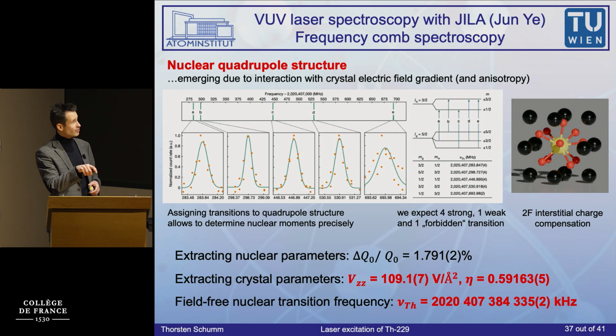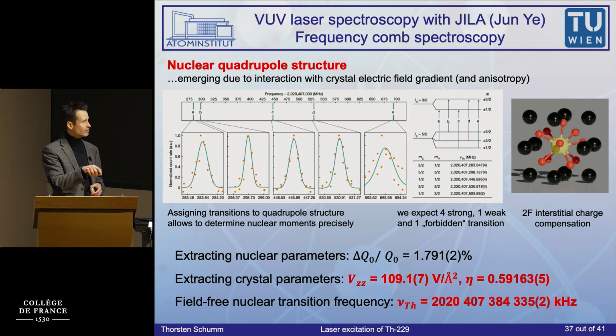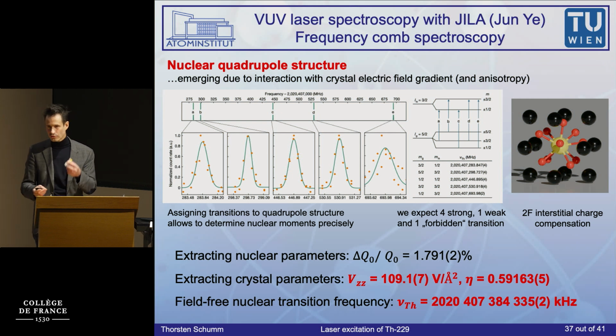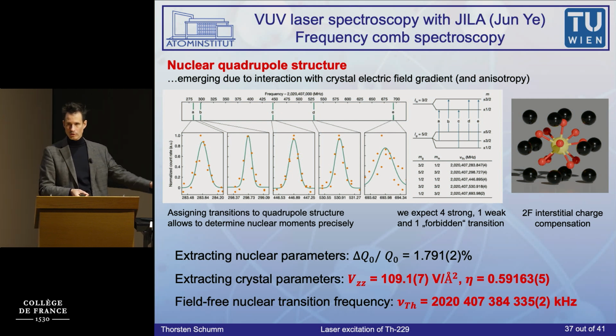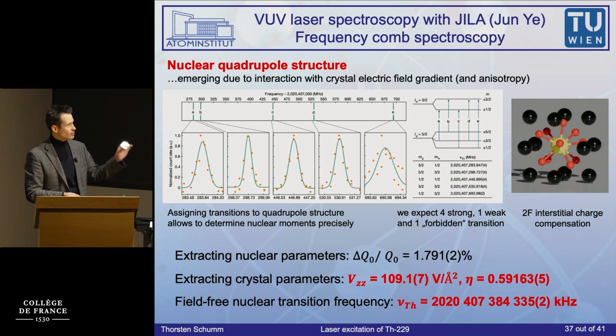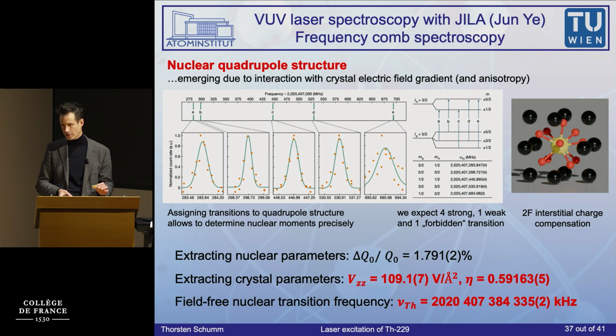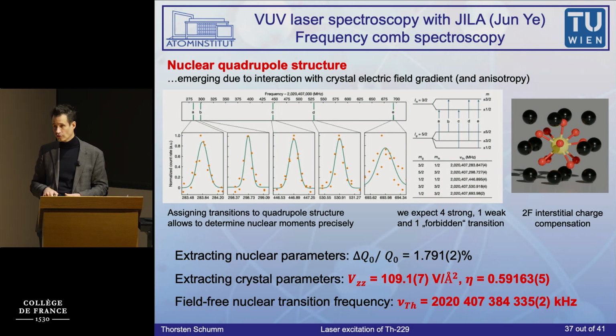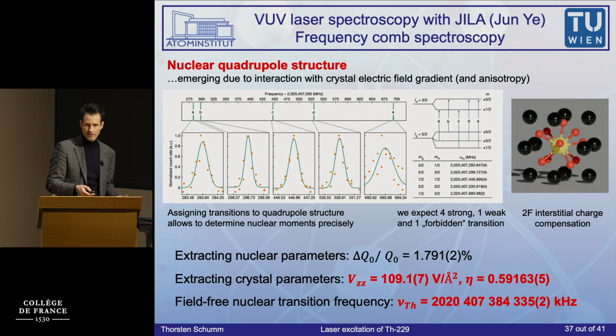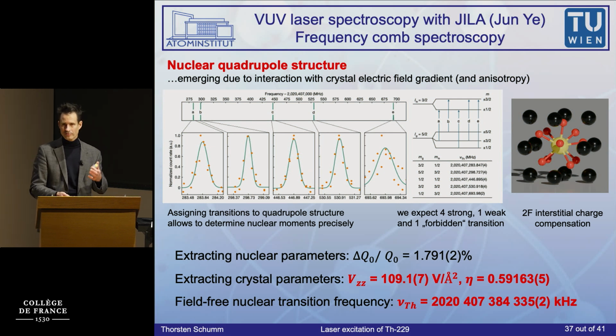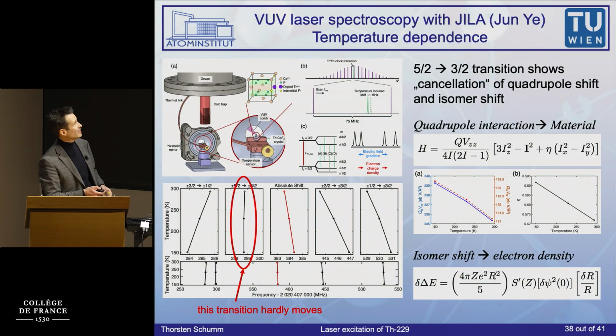All the positions of these lines depend on these material parameters. That means if I use a different crystal, the lines will be different. And not even that, if I use the same crystal at a different temperature, the lattice will shrink or grow a little bit with temperature. These parameters will change, and that means my clock transition is temperature dependent. That's not as shocking as it may sound, because that's also the case in atomic physics or ion physics. But let's have a look at this.